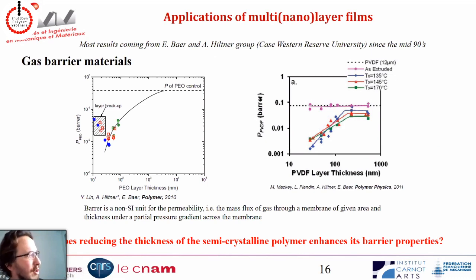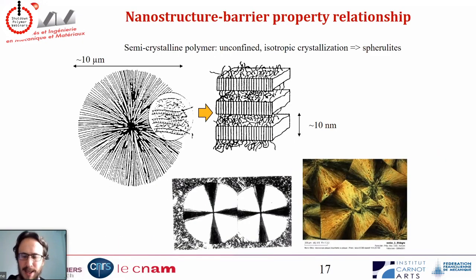So now the question is why reducing the thickness will enhance the barrier properties. You probably all know that when you don't confine your polymer and you let it crystallize isotropically, it will usually form these nice structures that we call spherulites, that are micron size, even 10 to 100 microns, and that are actually made of lamellas that are really thin, about 10 nanometers in thickness, and really long. You have this assembly of lamellas that form a spheric shape.